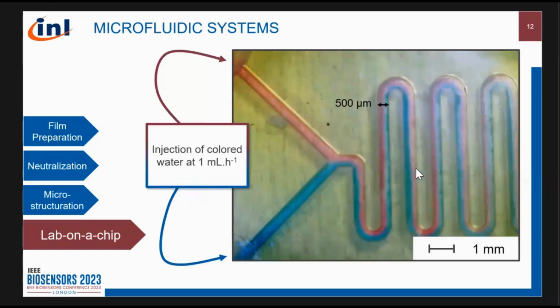Here is another more complex example of the kind of system that we can obtain from Chitosan. It is a Chitosan film that is bonded to a glass slide, and we injected in 2 different inlets, both red colored water and blue colored, with a flow rate of 1 milliliter per hour. You can also observe that the Chitosan film is highly transparent, so it's enough for our applications.